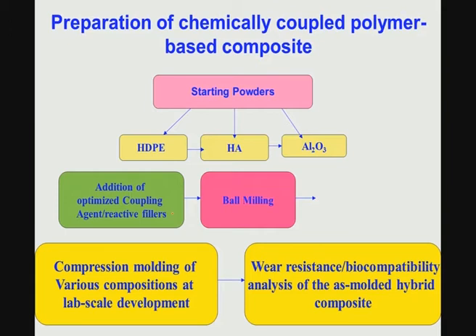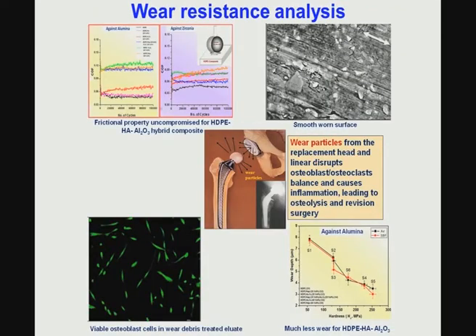So, there are three starting powders, high density polyethylene, hydroxyapatite and alumina, and then you do ball milling. Now, as you see, high density polyethylene has a very simple polymeric chain, carbon hydrogen, hydroxyapatite has a different organic inorganic composition, alumina has a different inorganic composition. If you do not couple these by chemical means like using a coupling agent or reactive fillers, you cannot do much in terms of achieving better mechanical properties. This coupling agent can be a titanate coupling agent, and so on. It essentially helps in establishing certain chemical bonding of the inorganic component with the high density polyethylene.